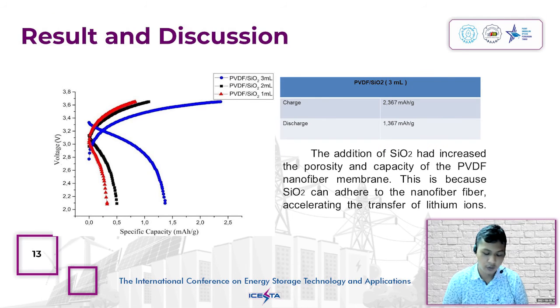Last is battery performance, charge and discharge capacity. The addition of SiO2 had increased the porosity and capacity of the PVDF nanofiber membrane. This is because SiO2 can adhere to the nanofiber, accelerating the transfer of lithium ions.